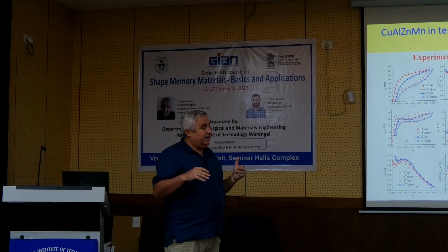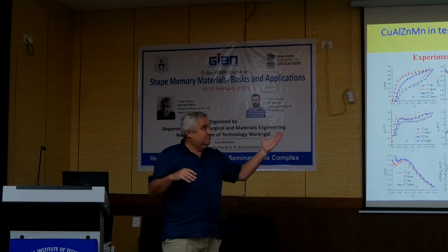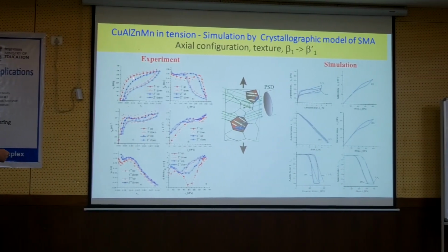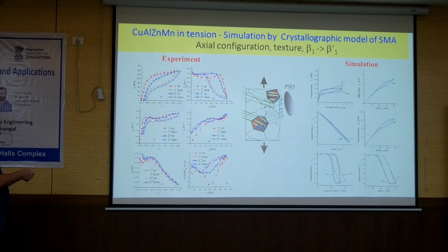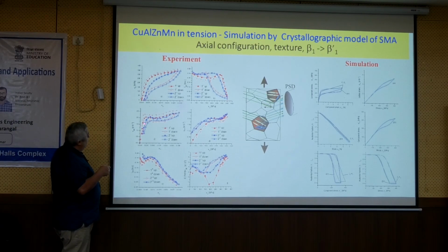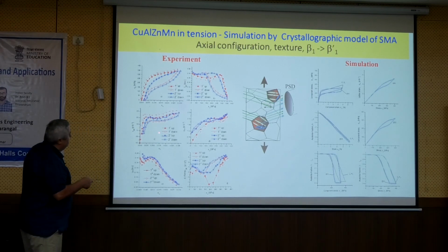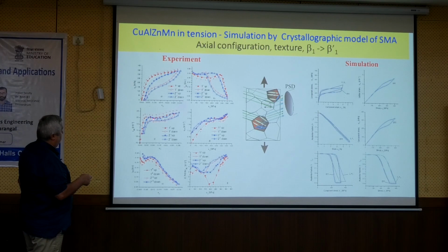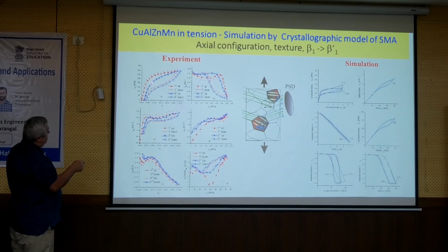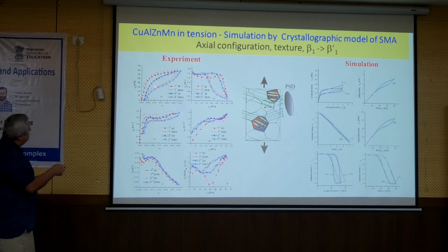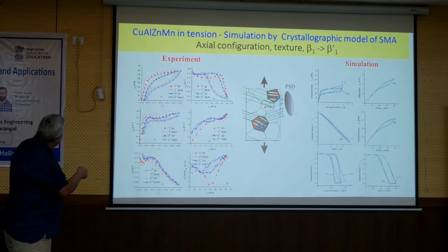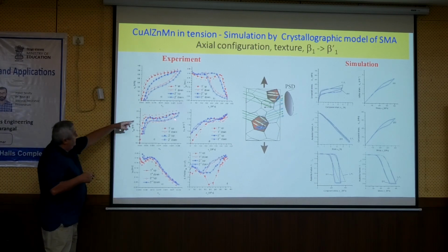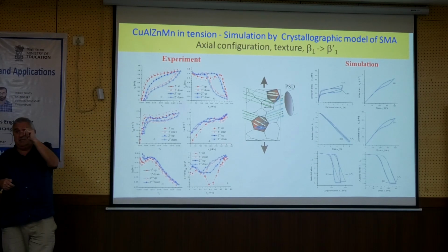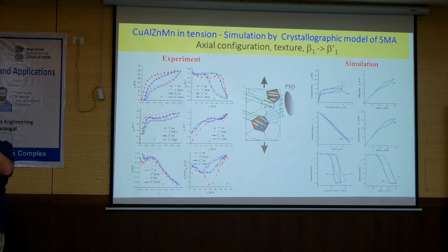But in case of this material, you have some plasticity, so it can survive maybe thousands of cycles, and you have this phenomenon with internal stress, which we can directly measure. It's a beauty. You see it here. This is the lattice spacing of some lattice plane in austenite. Macroscopically, the difference between the red and blue is something like 100 megapascal almost. No, it's less. But in case of lattice plane, the peak shift is exactly the same, because the peak shift inside the material measures the external stress plus internal stress.